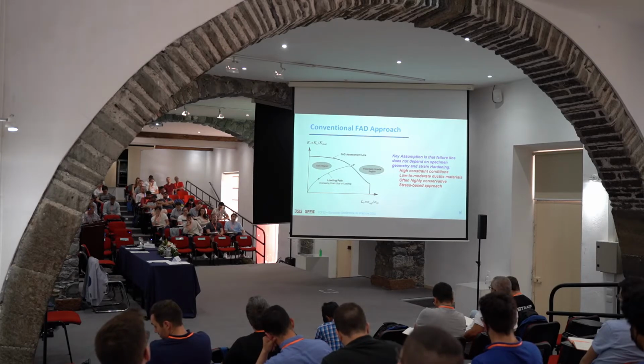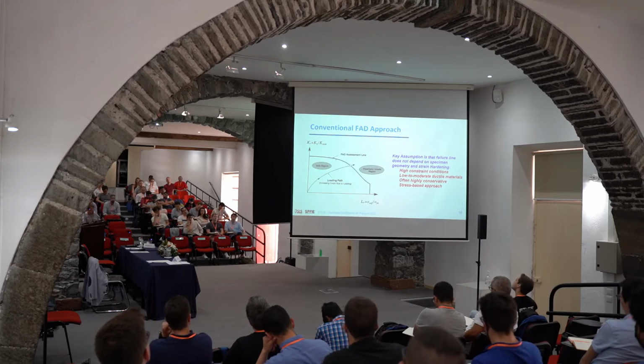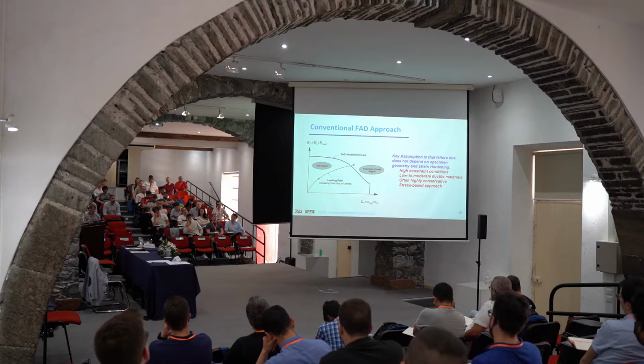Most common is the yield stress. And the key assumption is that the failure line, which is this one, does not depend on specimen geometry. It's a very strong assumption. Toughness depends, or I should say, fracture toughness does depend on specimen geometry.